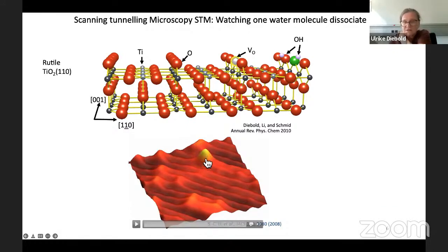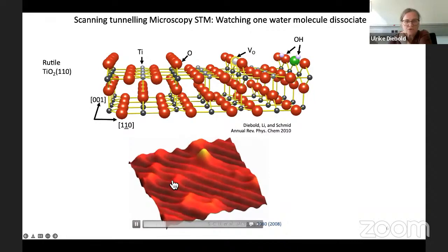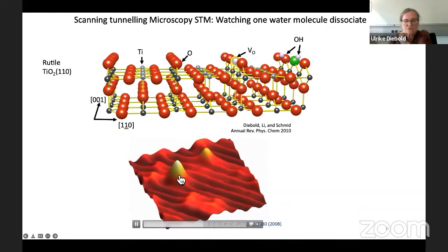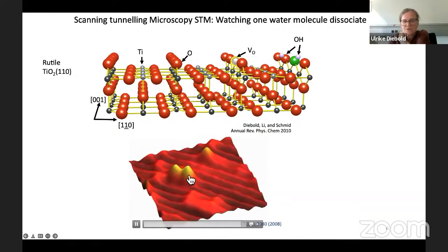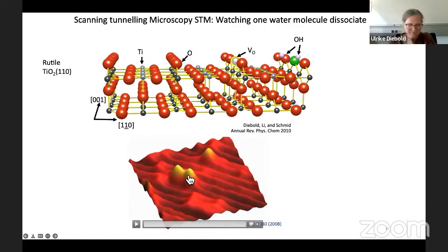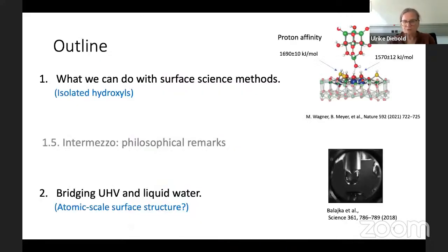And then I show you this movie, and in this movie, one single water molecule comes, probably hops around on these titanium rows, dissociates, and makes 2 hydroxyls. If you look here, there's some oxygen vacancies, 2 OH groups are formed and then move apart. So, very simple chemical process, right? A dissociation of one water molecule, but with really intricate insights. So this is experiment, right? This is not calculations. This is really experimental. So that's what we do.